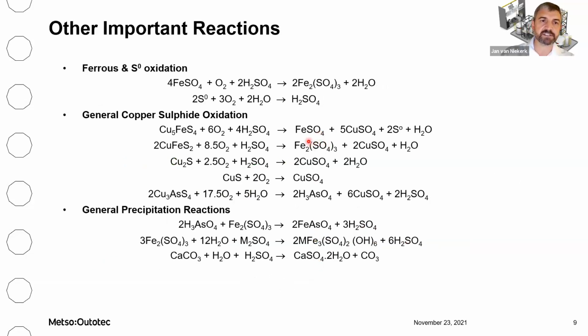Other important reactions during bioxidation are ferrous and elemental sulfur oxidation. Ferrous is for the regeneration of the ferric, that's the oxidizing agent, and elemental sulfur to produce sulfuric acid. As you can see, the reactions for the oxidation of copper sulfide minerals are fairly similar to the standard pyrite and arsenopyrite. And that's why the process can also be used for copper sulfide oxidation. There are a few general precipitation reactions that will also take place either in the BIOX reactors or following BIOX during the neutralization step. The most important one being the precipitation of arsenic in the form of ferric arsenate, as well as the precipitation of iron and the remaining sulfides as the basic metal sulfate and gypsum.